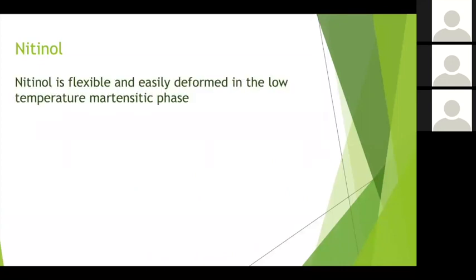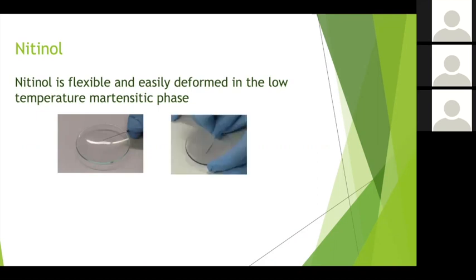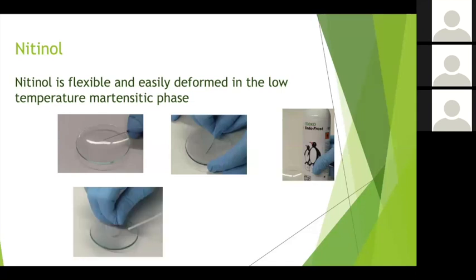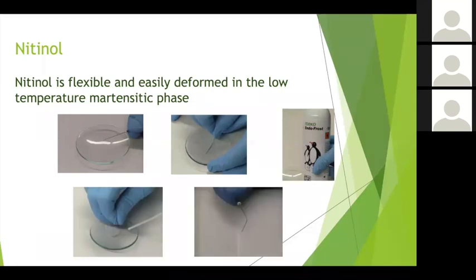So nitinol itself is really flexible. We can easily deform it in low temperatures. So if I have a low temperature, I can convert austenite into a martensite phase. This is kind of a cool party trick. If you take a little Petri dish and you have your straight file, and I bend it, meaning I put pressure on it and bend it, and then I take something like Endo Ice, in Europe they use Endo Frost, and I cool that point at the bend, I can actually put a file in a martensite phase at the bend, and it'll hold that phase for a little bit till it warms back up.